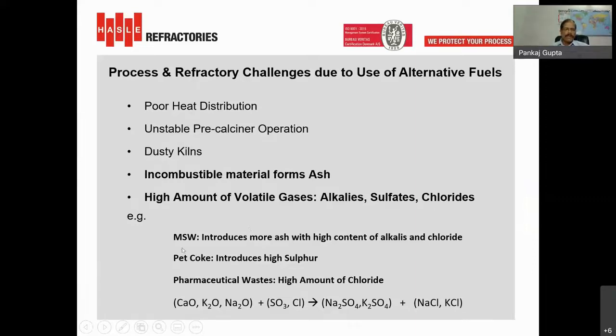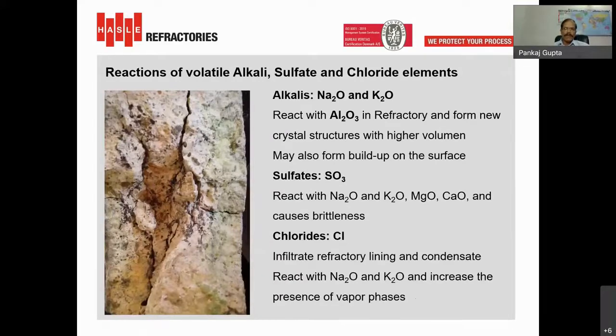We can see, when we are using more and more municipal solid waste, MSW, it introduces more and more ash and a high content of alkalis and chloride. And when we are using pet coke, it is introducing a high amount of sulfur in the system. And when we are using pharmaceutical waste, it is introducing a high amount of chloride in the system. This way, when we are burning alternative fuels, different types of gases are introduced in the system. So how are they impacting the refractory?